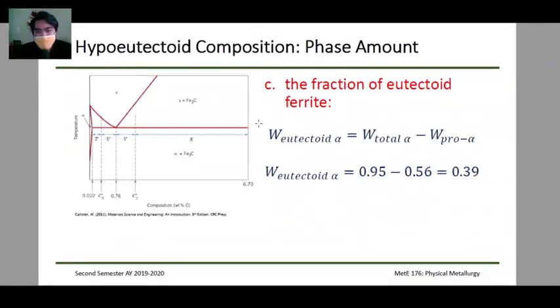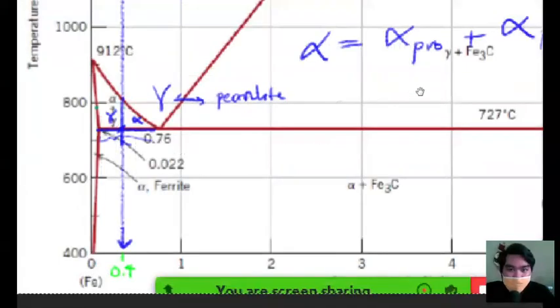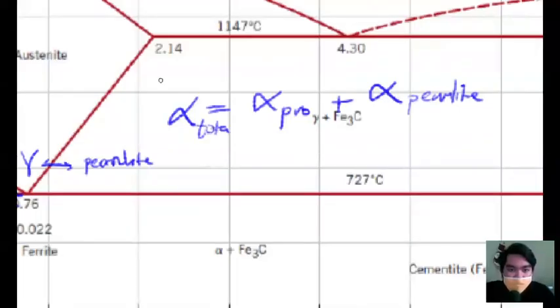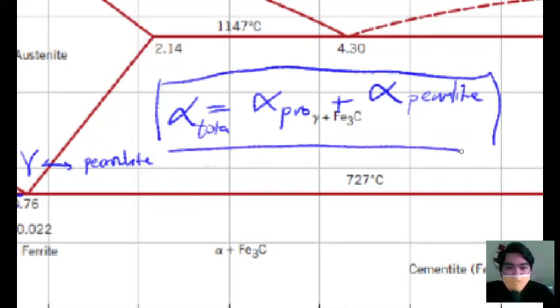Then lastly, what is the fraction of eutectoid ferrite, which is the ferrite in the pearlite mixture? We just get the total alpha, which we computed earlier, minus the composition of the pro-alpha, which would give us 0.39. So again, what we computed earlier is the total. We know this total, and we just computed the pro-alpha, so we should be able to get the alpha in our pearlite, or in the eutectoid composition.